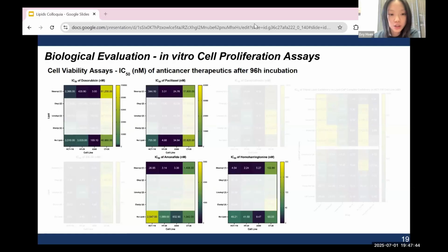We suspect that this is a result of our sterol dilution going bad over time, rather than an indicator that the trend is irreplicable. We think this is the case because we ran this assay a couple weeks before the initial 3 cell lines, and the sterol lipid appeared visibly less soluble in the dilution plate after a few weeks. Sterol itself was our most solid lipid and had solubility issues throughout the initial assays as well.